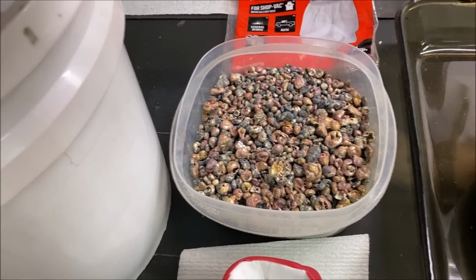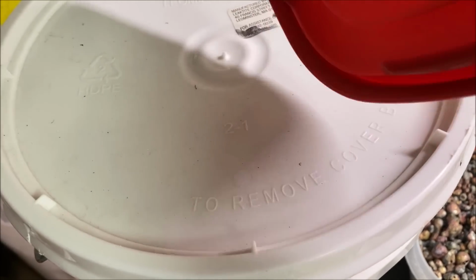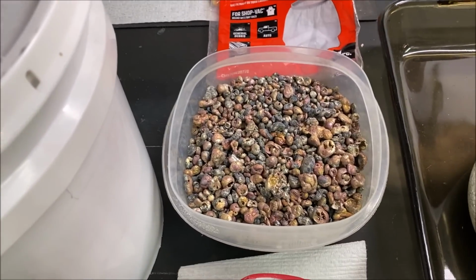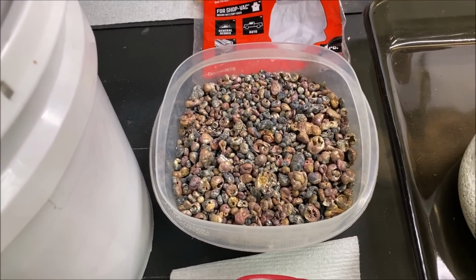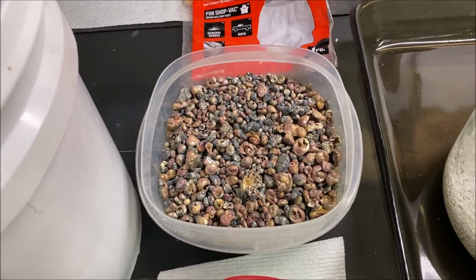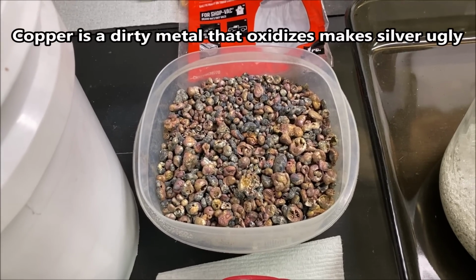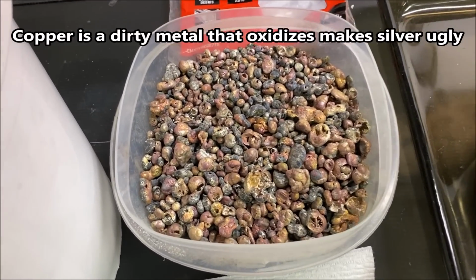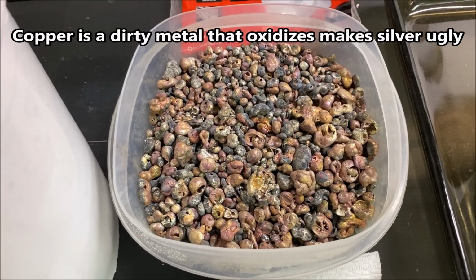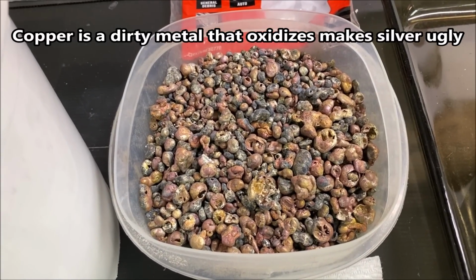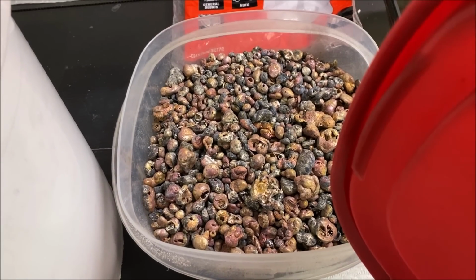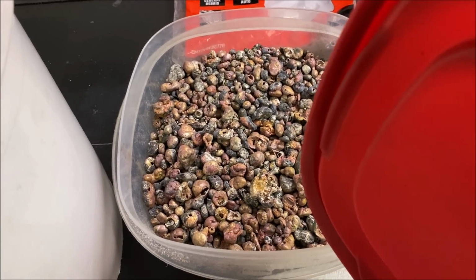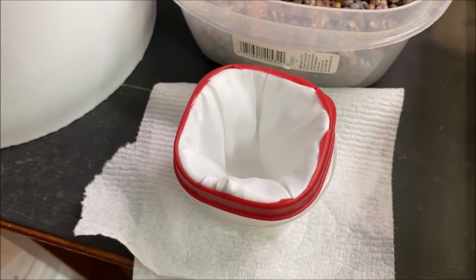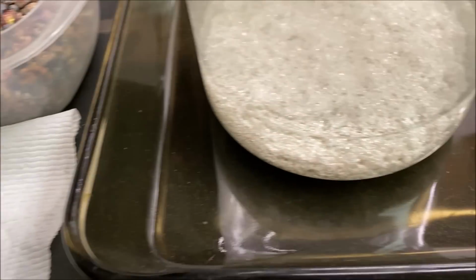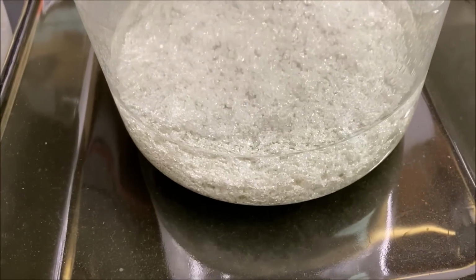This is impure silver made by melting this cement silver and pouring it into water, and it forms these granules. That's about 98 to 99% pure silver there. It's real ugly because that 1% copper reacts with the atmosphere and creates that ugly appearance, but that's about 99% silver there. And so we run this through an anode basket in the silver cell, and then we convert this to pure silver crystal.